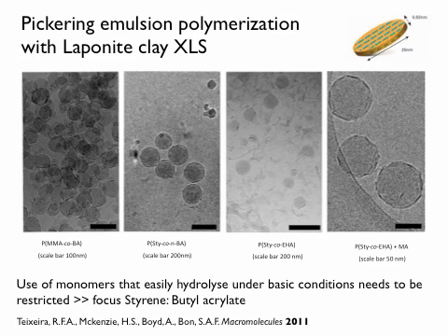That's why in all of these images, you see the clay platelets really clearly at the edges, where they stand like this, of the spherical particles, and when they're dispersed through the matrix. The important thing with this particular sample was, this was a type of Pickering emulsion polymerization system in which we wanted the clay platelets to be on the surface of the particles, but you have to have proof for that. These clay platelets are a pain to separate by any other technique. Because they stack a bit like cards, it's impossible to separate this with disk centrifugation. So the only way to check whether they're on or off is cryo-TEM.